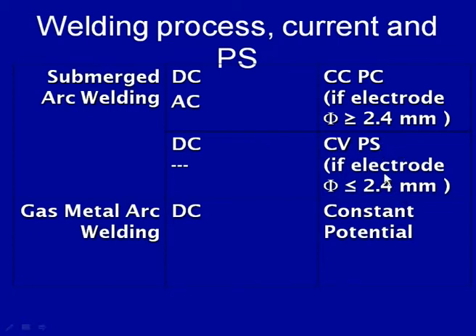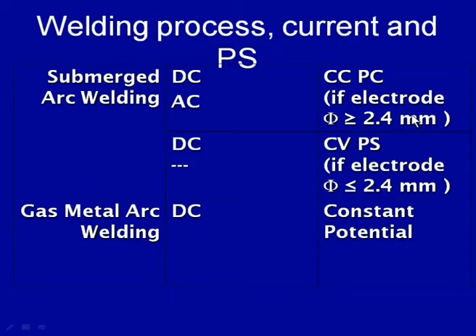So, constant voltage power sources are used for small diameter electrodes with a DC current supply, and otherwise constant current power sources are used with electrode diameters greater than 2.4 mm, where it is not possible to use the self-regulating arc to get a uniform arc length.